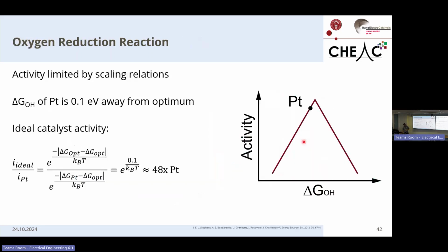So let's grab the oxygen reduction reaction as a context again. The oxygen reduction reaction is limited by scaling relations. And the binding energy of the OH intermediate on platinum is 0.1 eV away from the top of the volcano. So the optimal activity of the ideal catalyst we can express in platinum equivalents, and that will be around 50 times the activity of platinum. So now we have an upper limit in how active our active sites can be.